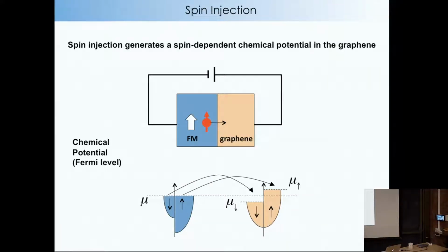So the injection works like this. You have more spin ups than spin downs in the ferromagnet. And when you apply a bias, then you're going to inject some electrons. And what happens is, since there's more spin ups, you're going to start filling the spin up bands faster than the spin down bands. And what happens is you start getting a chemical potential, which is like a local voltage. It's just going to be higher for spin up than spin down, right? So it's almost synonymous to have a splitting of this spin-dependent chemical potential correspond to your spin density, okay? And this is why the measurement works. So you get a splitting between up and down.